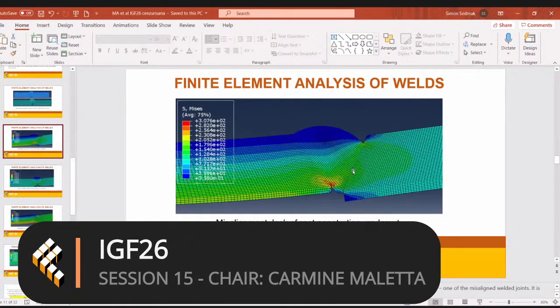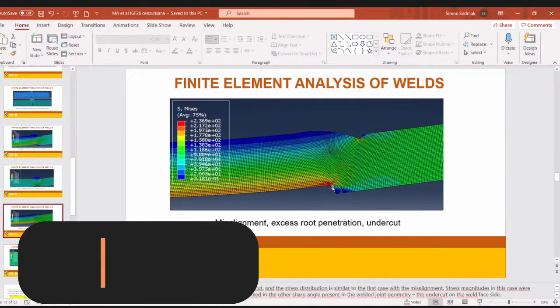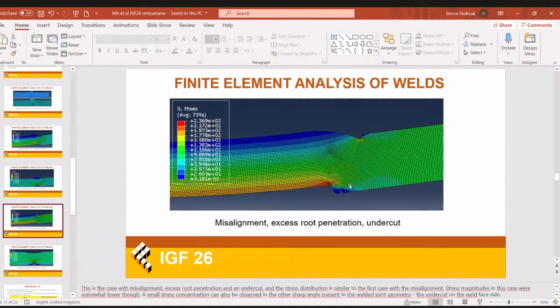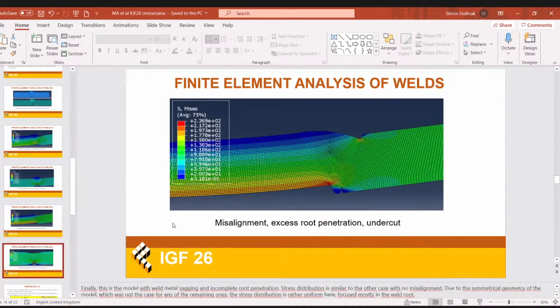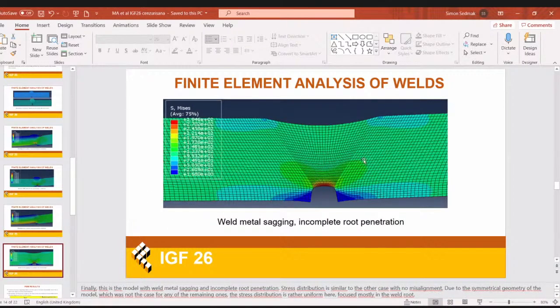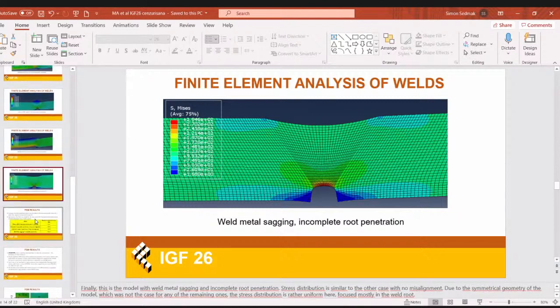Now, these are the results for the different cases. This, for example, is one of the misaligned cases, and this was the other one. And you can see the stress concentrations in the more or less expected locations, where there were sharp geometric transitions, but also slight stress concentrations in the undercut as well. And here is an example of one of the non-misaligned specimens that only had weld metal sagging and incomplete root penetration, and of course significantly more favorable stress distribution.